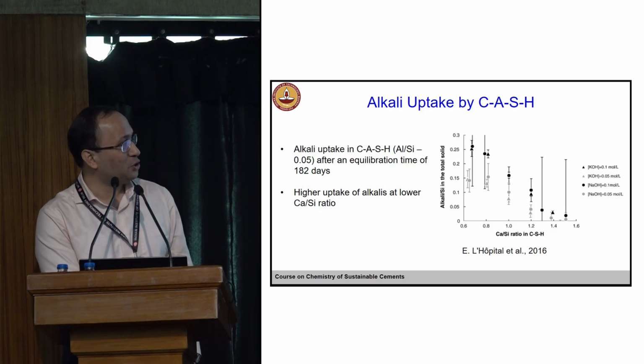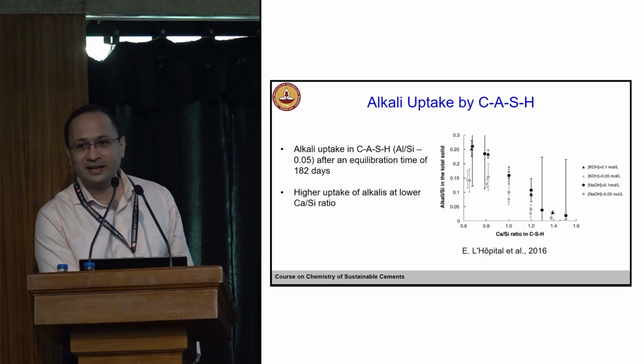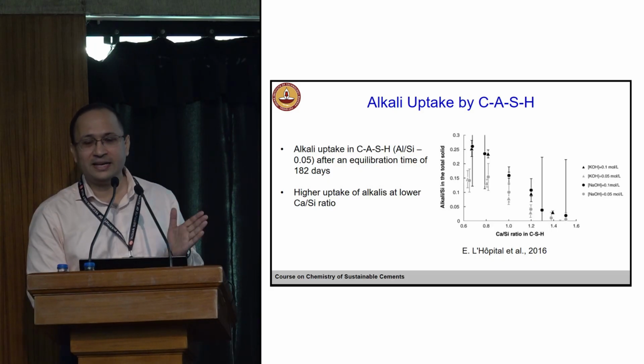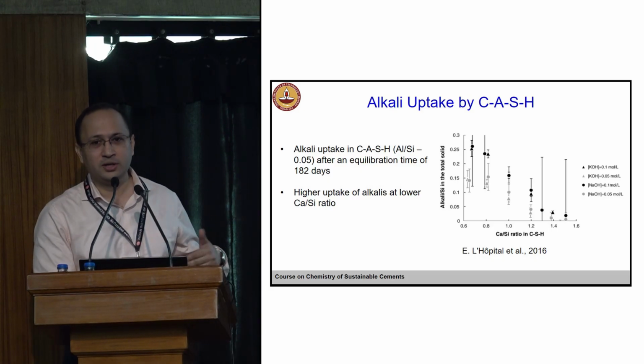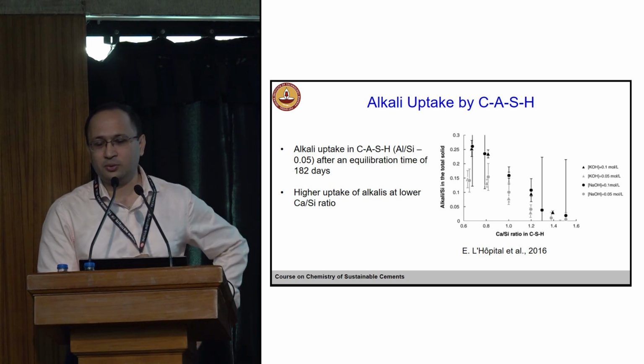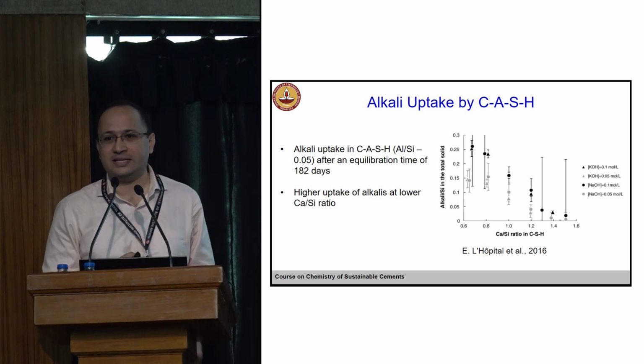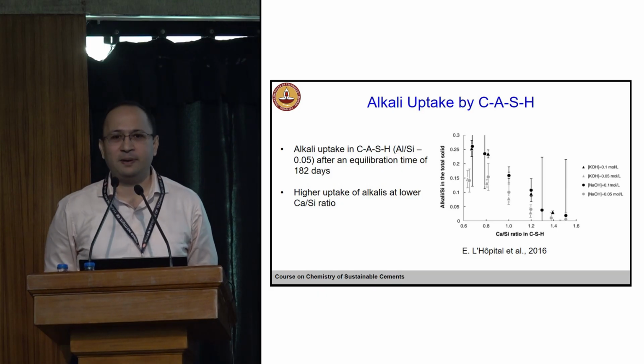So C to S ratio, right? Say if you look at the C to S ratio of CSH, if it is at 0.8, for example, the alkali to silica ratio in the total solid is significantly higher than in this case. It's pretty obvious that as C to S ratio is reduced, alkali to silica ratio increases. So it can bind more alkalis. And I said it has implications on durability.